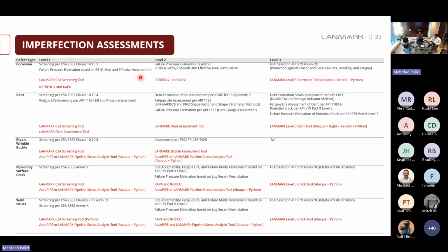If the feature was still failing at level one, then we can go to level two and do an RSTRENG and KAPA modeling over that feature. And we can also go to level three and do a finite element analysis based on API 579 Annex 2D. Similarly, for the rest of the features, we have methods for doing analysis in three levels, let's say for dent, buckle type features, cracks, and crack-like issues.